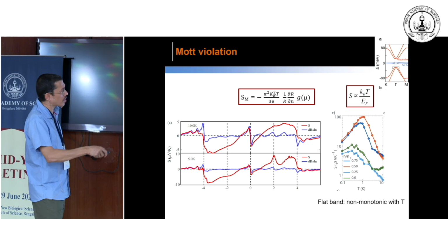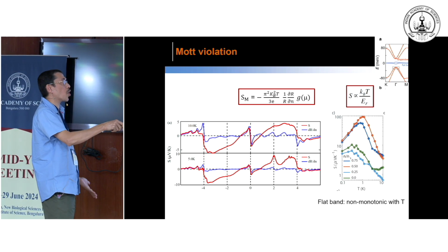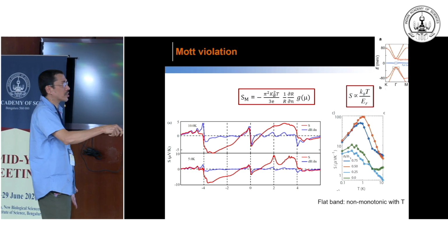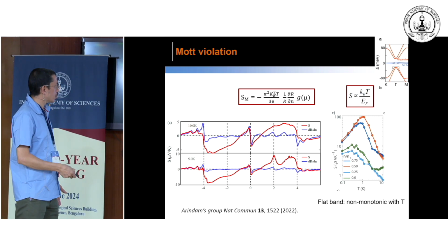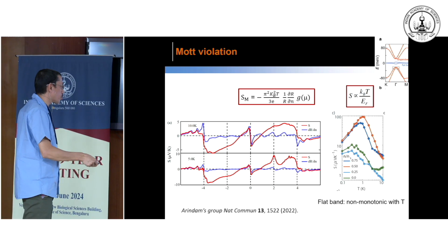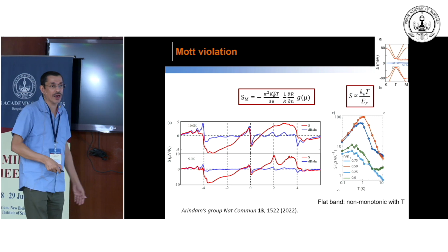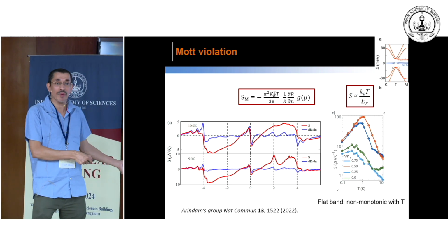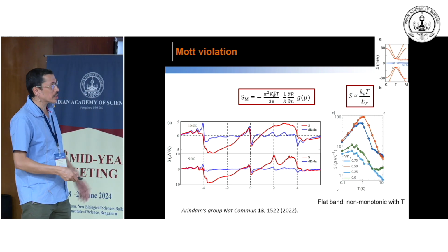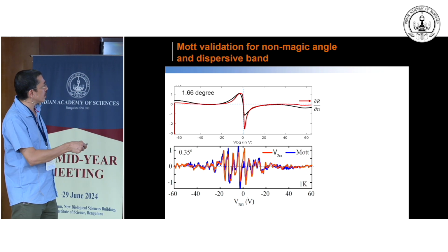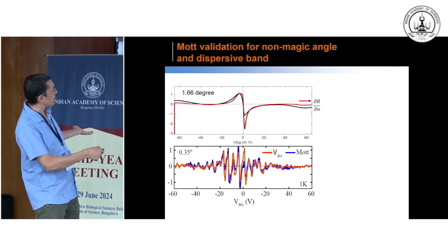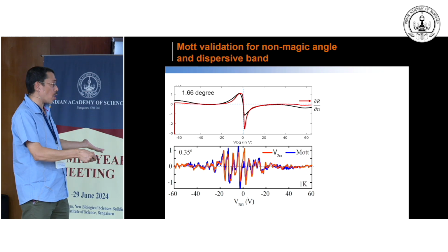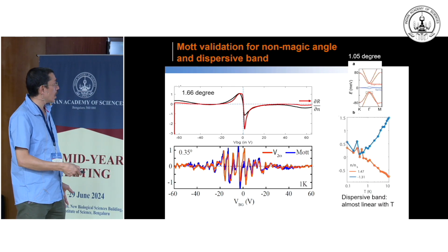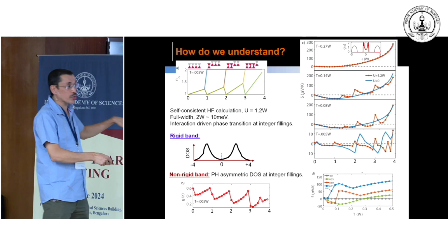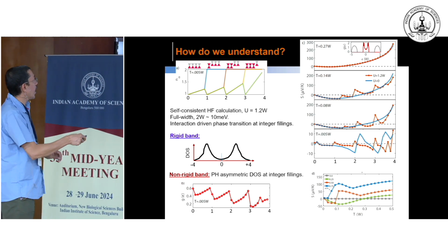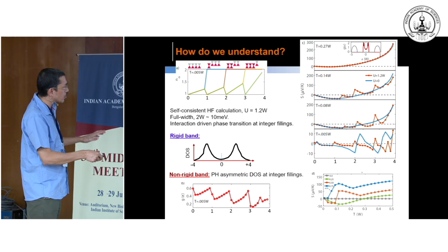Not only that, the temperature dependence is very unusual. Mott is supposed to give you linearity, but here you can see a very non-linear behavior. In fact, at the same time, other groups also showed there is Mott violation, not only in the magic angle device, but also away from the magic angle. If you go very far away from the magic angle, at 1.66 and 0.35 degrees, the Mott formula actually holds, there is no problem.